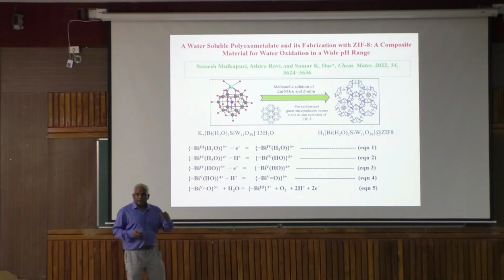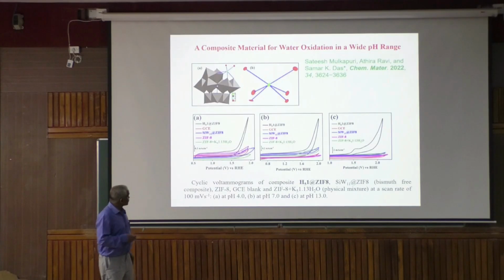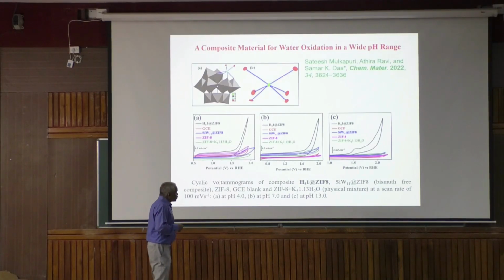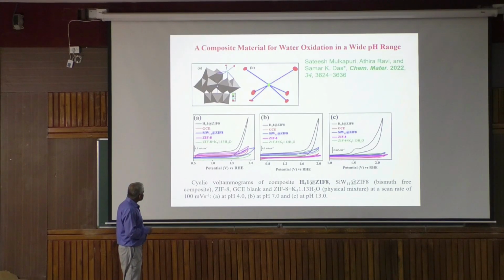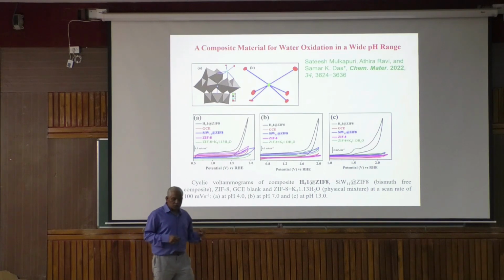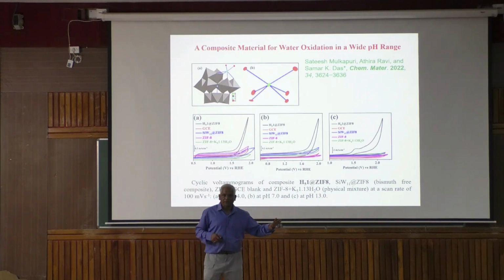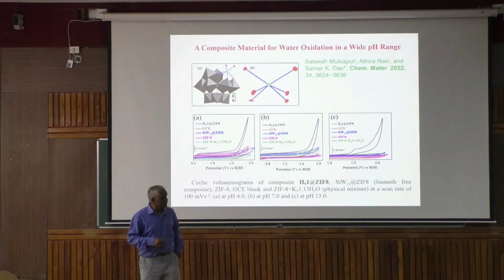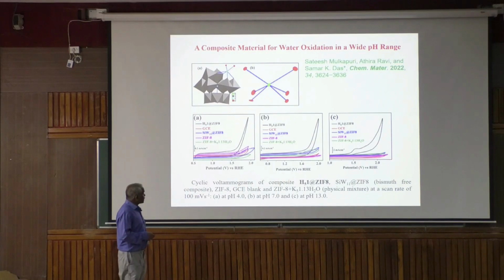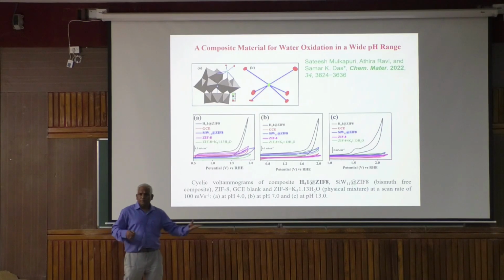Then we wanted to check really the electrochemistry, water oxidation. Now you see, a very interesting thing happens. We can use it in a very wide pH range, from pH 4 to 7 to pH 13. At pH 13, one polyoxometalate, you cannot imagine, it will decompose, just coming back to monomeric oxo molecules of tungsten. But here you can do 100 cycles at pH 13, 500 cycles at neutral pH, and even 1000 cycles at pH 4. pH 4 makes sense. Polyoxometalates are very stable.